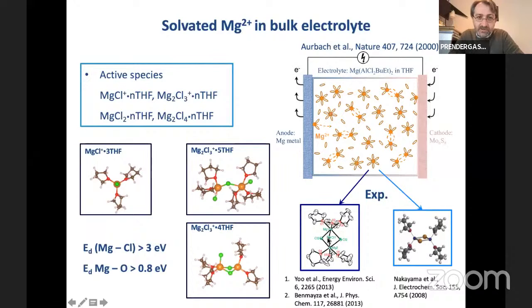And so you can do the simplistic cluster models in vacuum and begin to explore the binding energies of these objects. But you realize very quickly for multivalent ions in solution, particularly when the solvent is not water, but some aprotic solvent, an organic species, in this case, THF, the binding energies of these species are huge. So the typical bonds, because they're strong ionic bonds between highly charged objects, they're in the multiple eV. And then even the polar oxygens, or whichever group might be the polar group of your organic solvent, those are quite strong bonds as well, much bigger than hydrogen bonds.